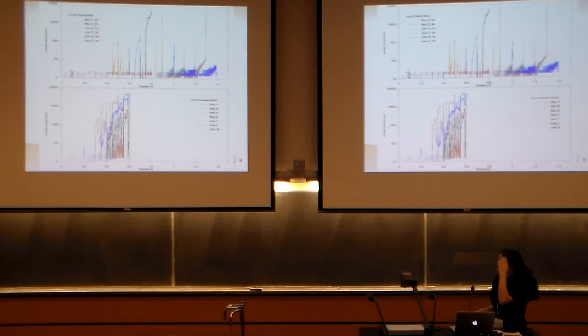So here's a bunch more of our data. These only include our 1, 2, and 3 hour treated wires. Our 6 hour treated discs haven't been included yet. All the treated samples are at the top, and the bottom ones are all untreated. They have the same scale of potential versus current. And you can see for the treated samples, overall, there's a lot fewer events, and a lot of them don't occur until much higher potential.